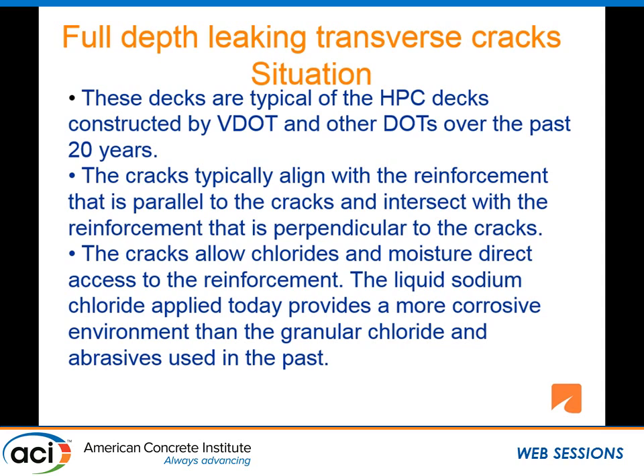Now, these cracks typically align with the reinforcement in the transverse direction, parallel to the cracks, and they intersect the reinforcement that's in the longitudinal direction of the deck. But these cracks are typically wider than 0.2 millimeters. Most of the time they're 0.5 millimeters. We've measured many of them, but 0.5 millimeters. Any crack that's as wide as 0.2 millimeters or wider is going to leak and allow chlorides into the crack.